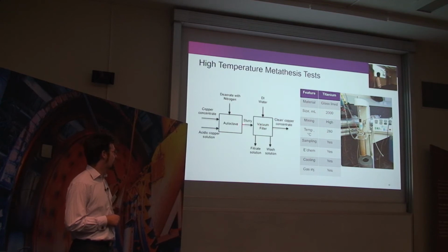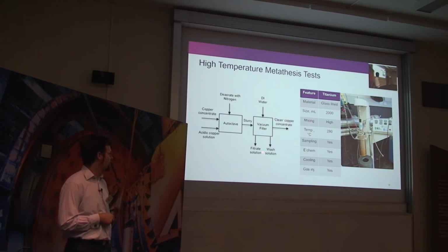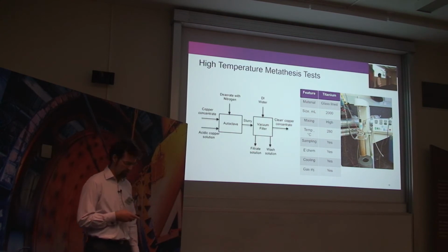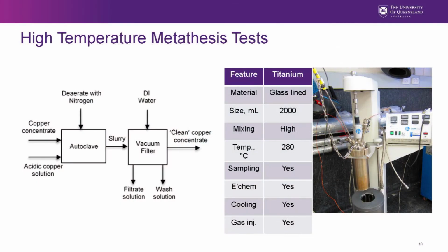After that reaction is done, we separate the solids and the liquids using vacuum filtration and wash the concentrate, and we get a so-called clean copper concentrate, and we get a wash solution and a filtrate from the first filtration. We're doing this in a titanium autoclave, which is resistant to chlorides to some extent. We have a glass liner. It's a 2-liter autoclave. The mixing intensity is reasonably high. The temperature could go up to 280. We have the capability for sampling hot, and we also have the capability for in-situ electrochemical measurements.